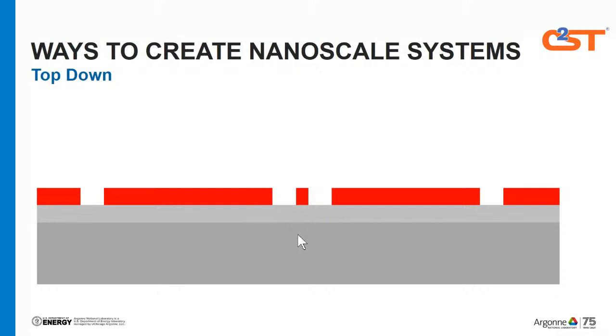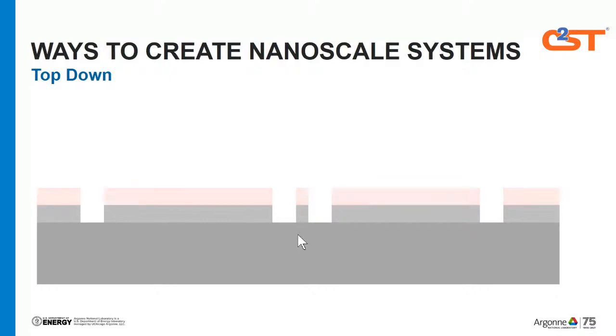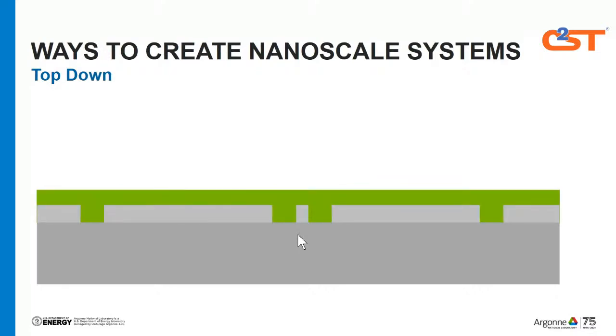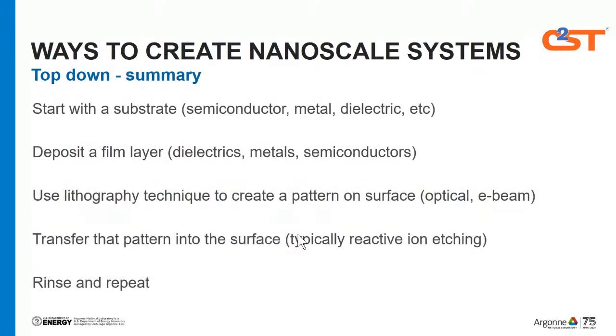And then once you've created a pattern in this polymer, you can transfer that into the underlying film, rinse off the polymer, deposit a different film, and repeat the process to make structures that are very complex. In a standard electronics process, you may do this somewhere between 30 and 100 times to realize your final electronic configuration. And now it's even advancing more, depending on what type of lithography you're actually doing.